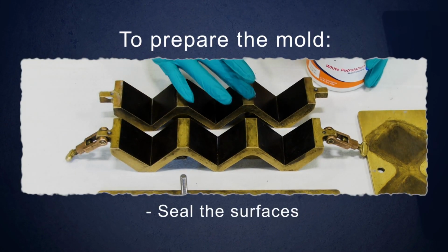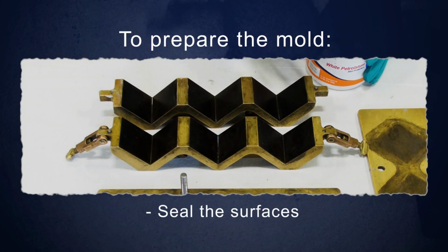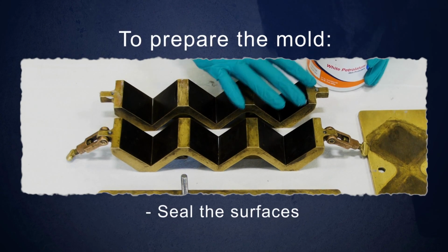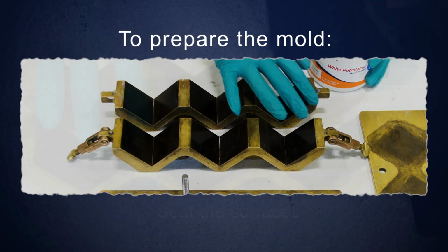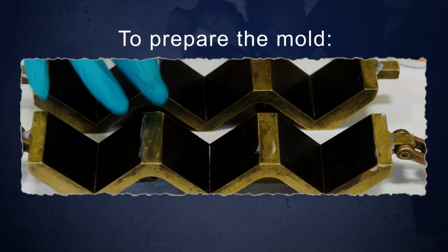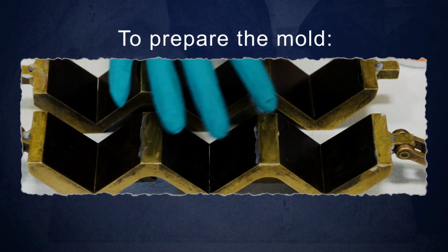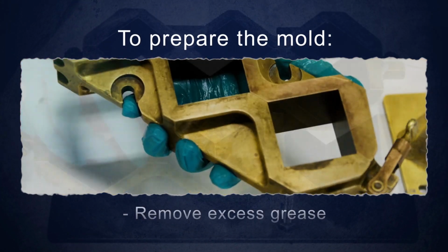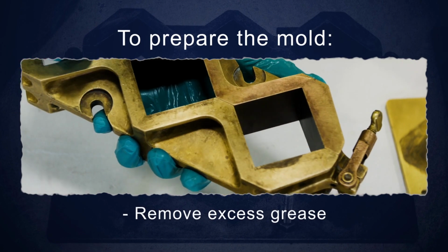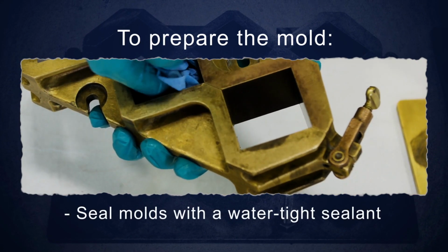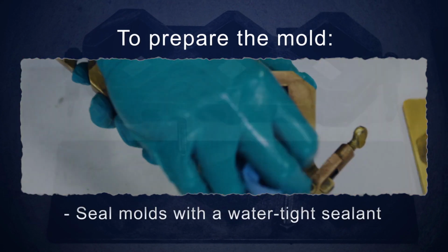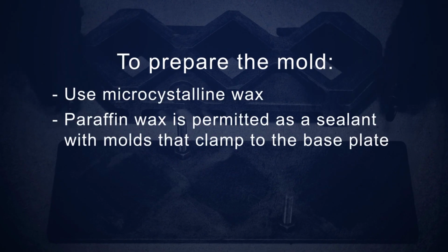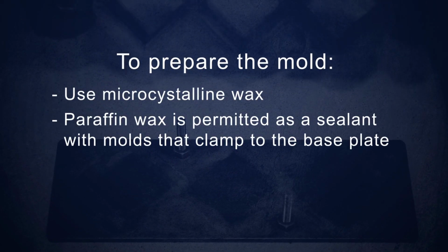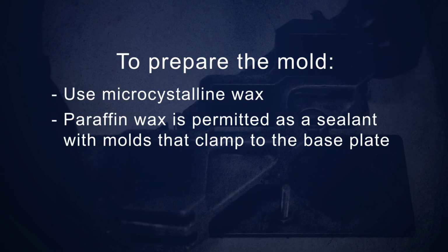Seal the surfaces where the halves of the mold join by applying a coating of light cup grease, such as petrolatum. The amount should be sufficient to extrude slightly when the 2 halves are tightened together. Remove any excess grease with a cloth. Seal molds to their base plates with a watertight sealant. Use microcrystalline wax. Paraffin wax is permitted as a sealant with molds that clamp to the base plate.